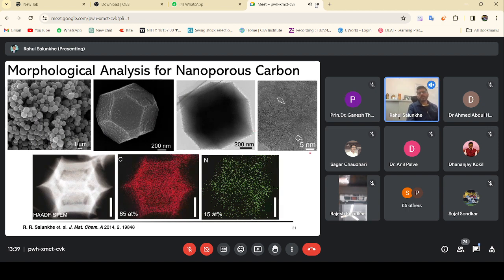The morphological analysis of this sample shows that they have an average particle size of around 1 micrometer. Further high magnification SEM confirms that the nanoporous carbon shows a symmetric geometry with a polyhedron type shape, and the particle size of these particles can be controlled by changing the reaction conditions.